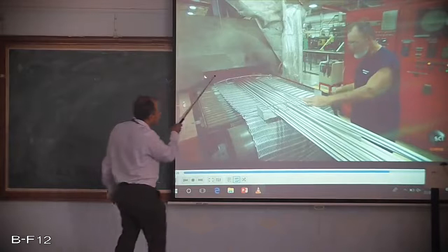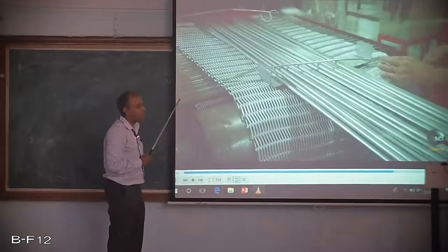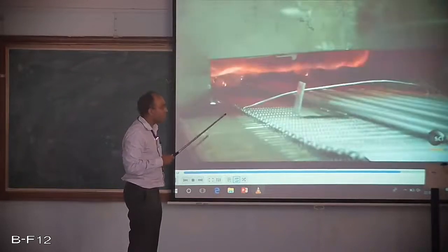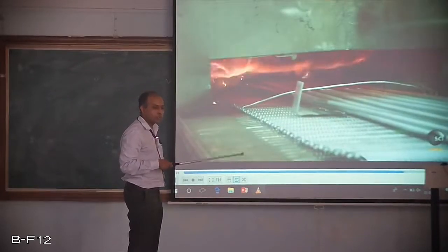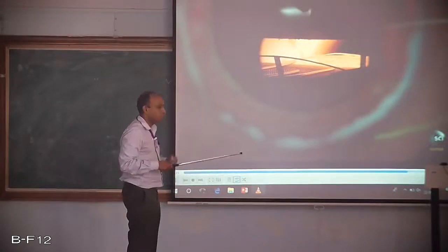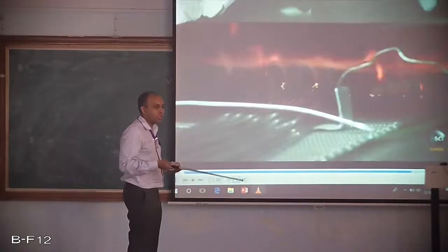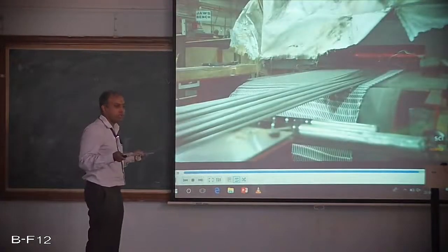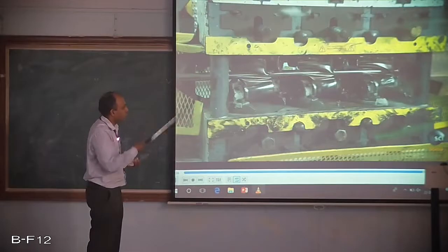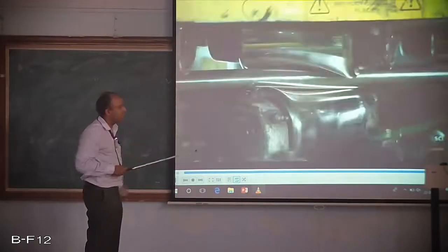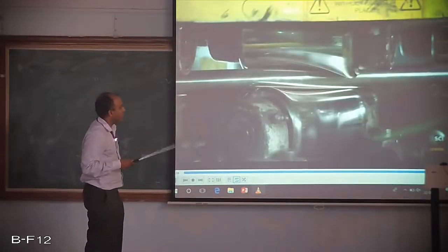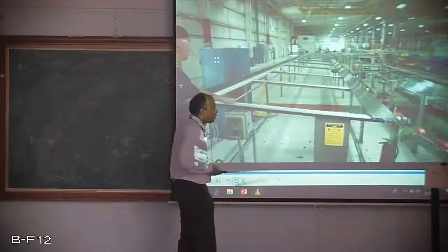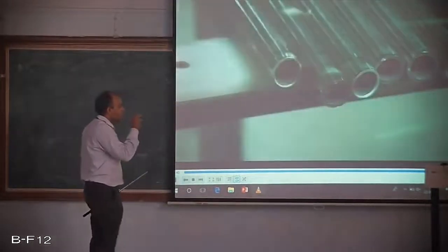Now we are giving the annealing heat treatment to this. Okay, annealing heat treatment. Why? Because drawing was a plastic deformation process, and it was done at lower temperatures. So it is a cold forming operation. So during that, strain hardening of the material takes place. Okay, residual stresses are generated within the material. So remove those residual stresses so that premature failure doesn't take place of this manufactured product. In this case, it's a tube or a pipe. That's why annealing is carried out. And once that is done, it is passed through this reeling, meaning some kind of rolling operation, to get the required dimensions.